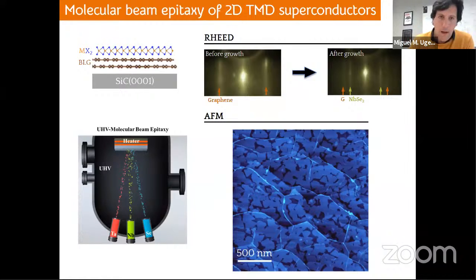So this is for those of you who are not familiar with the molecular beam epitaxy methods, I will just tell you that we can grow these materials. We have mostly grown these materials on bilayer graphene on silicon carbide for these experiments. We have also done it on single layers of hBN on an iridium 111 substrate that I will show you in a few minutes. But in general, the MBE growth is based in UHV, and we grow it from the pure ultra-pure elemental materials.